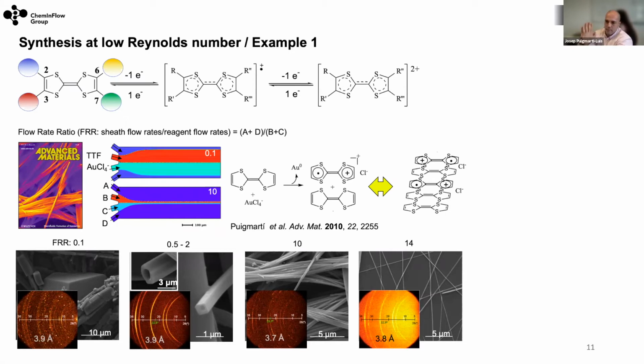And this is very important, not because we did it, but I think this clearly proves that, if you remember what I showed before, I always had to change the functional groups in this position in order to control the stacking of the TTF molecule. And here what we prove is that only changing how they mix, so how the fluid streams behave, we are able to change the pi-pi stacking distance of the final product. And of course, also the morphology.